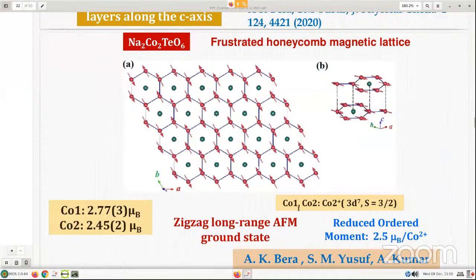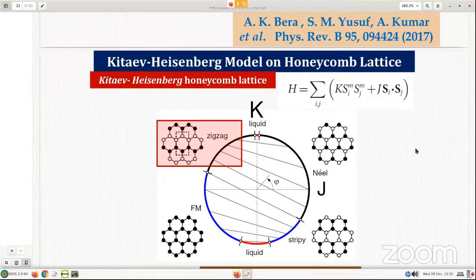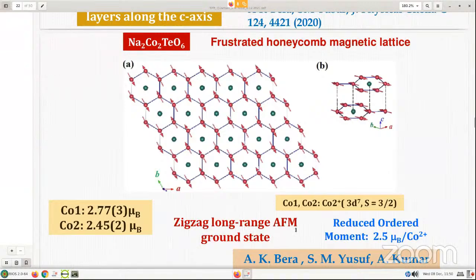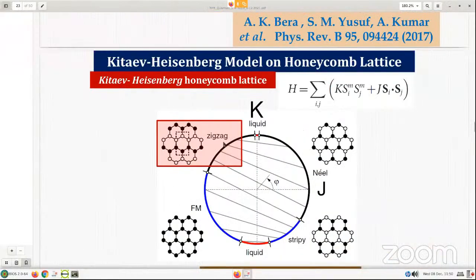What I would like to point out is that even at 1.5 Kelvin, at both the cobalt sites, the moment is reduced, because S equal to 3/2 would give 3 Bohr magneton. So even in an ordered system we see some kind of effect of frustration. As I told you in the previous viewgraph, this structure is the zigzag long-range antiferromagnetic ground state. If you put that in this phase diagram of the KJ model, our system falls here, a zigzag antiferromagnetic state. It is not a pure spin liquid, but it is very close to that. It only means that K effectively is there, but J cannot be neglected at all.